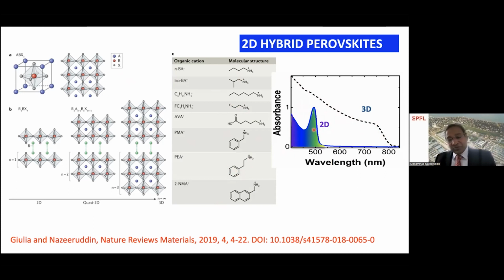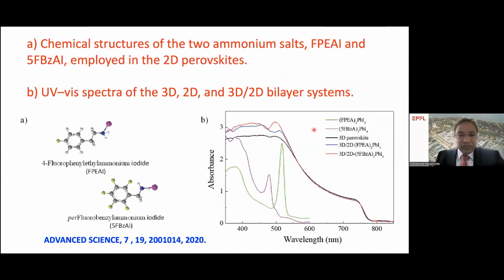So what you will see in my presentation is combining these two strategies: keep the three-dimensional perovskite and coat it with the two-dimensional perovskite to increase the stability. That's what you will see. The two-dimensional perovskite absorption spectral properties are shown here. I have taken two examples. Fluorophenylethylamine is one cation I have taken as an example. And the second example I have considered is pentafluorobenzylamine. Why have I taken these cations?